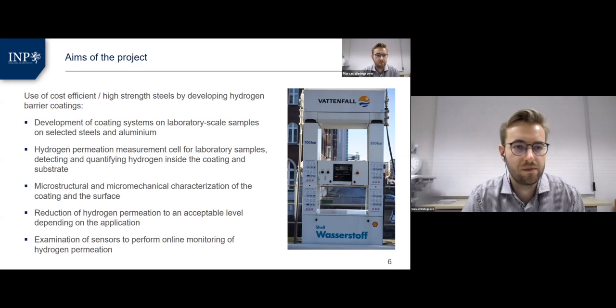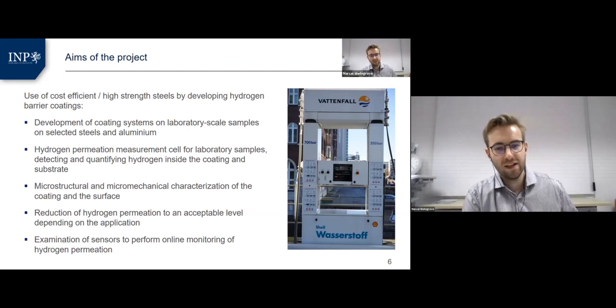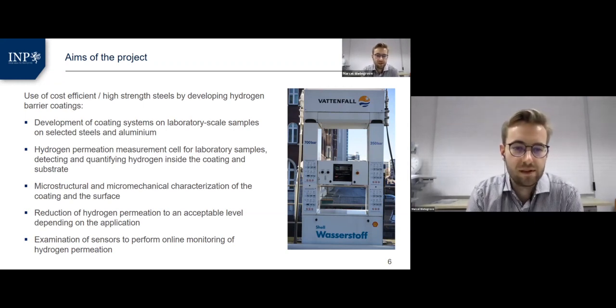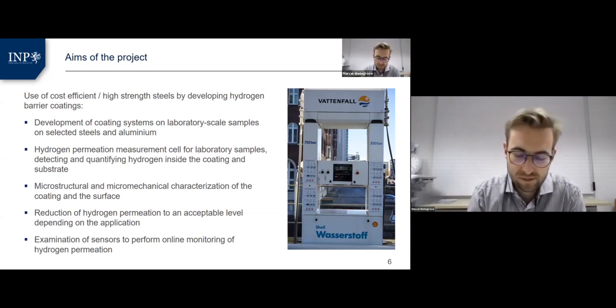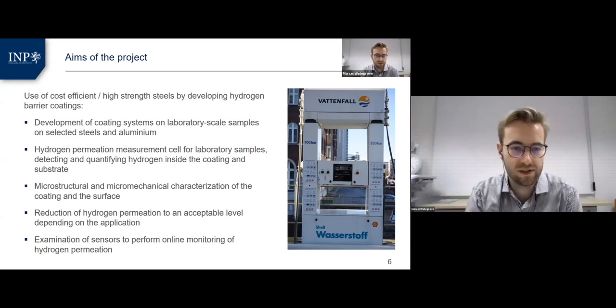To achieve that, we are developing coating systems on a laboratory scale, both on steel substrate and on aluminium. We measure hydrogen permeation inside a specially made cell on these laboratory samples, detect and quantify hydrogen both inside the coating and the substrate. Another vital part is the microstructural and micromechanical characterization of the coating and the surface, and finally achieving a reduction in hydrogen permeation below an acceptable level, depending on the respective application. And further down the road, we examine sensors to perform online monitoring so that hydrogen permeation can be monitored.